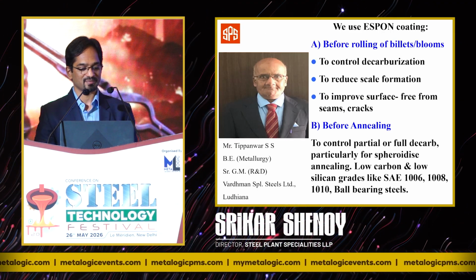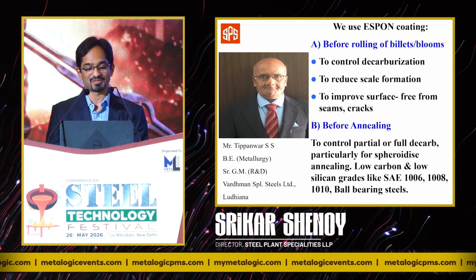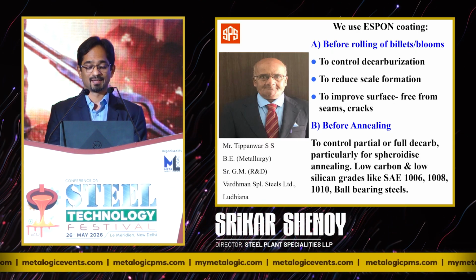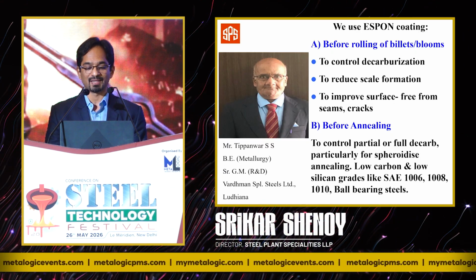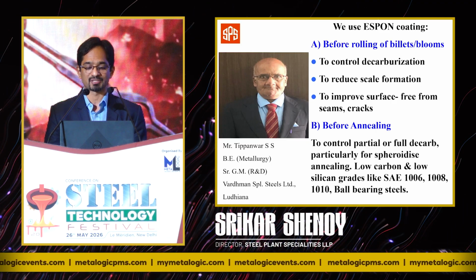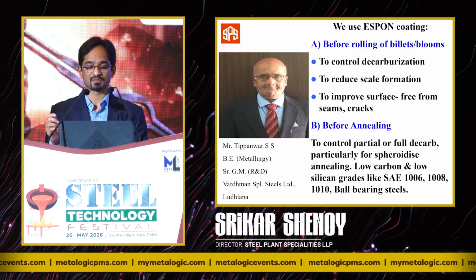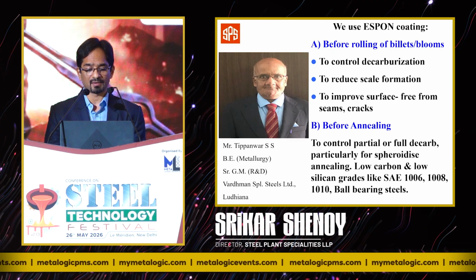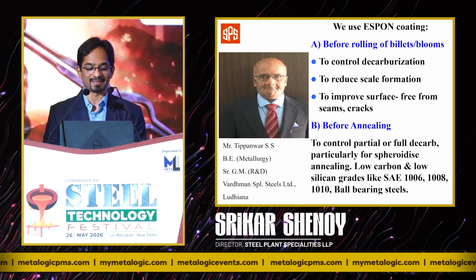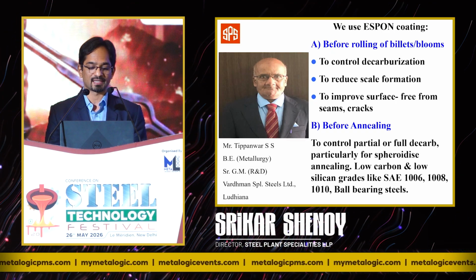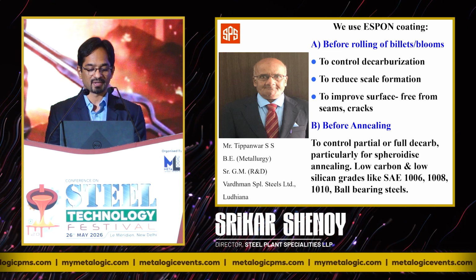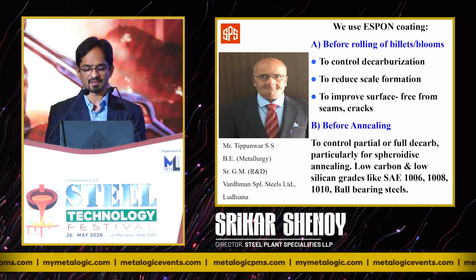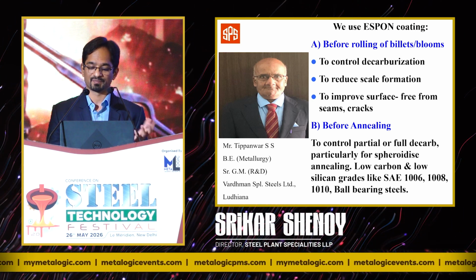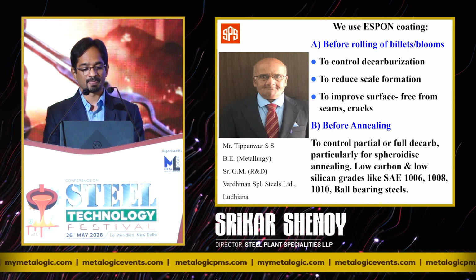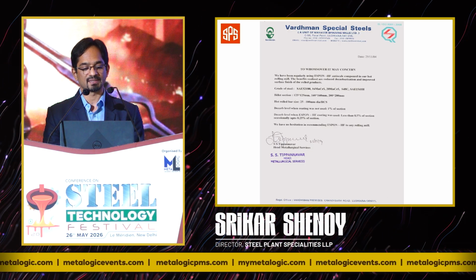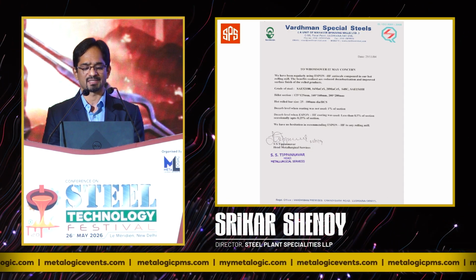A tribute to the senior metallurgist at Vardhaman Special Steel. The gentleman has extensively used coatings at the billet stage to control decarburization, to reduce scale formation, and to improve surface from micro cracks. And again, some of the hot roll products need to be heat treated. So before heat treating, the coatings are given to control decarb and various others. Various grades: ball bearing steels, 9254, spring steels, whatever you may have. Some of the grades here: automotive steels, SAE 52100, 16MnCr5.